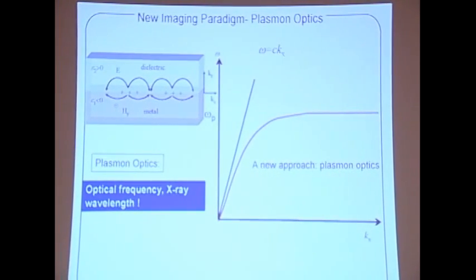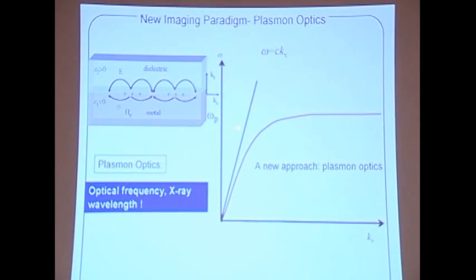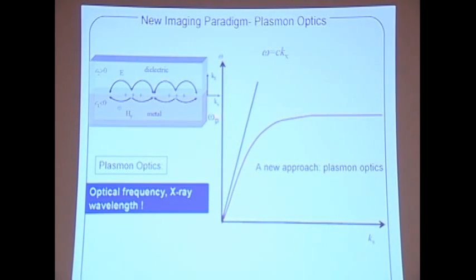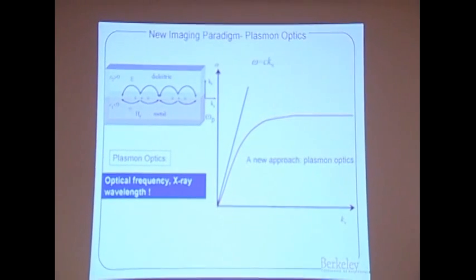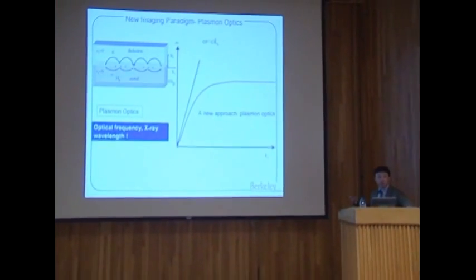Surface plasmons, as the red curve shows here, offer a different approach, where you can excite at visible frequency or a little bit of UV a very large k vector. So if you excite around here, a very large k vector surface wave can be excited. And that gives you so-called optical frequency and X-ray wavelengths. Now, X-ray wavelengths really means this large k vector and surface waves. So those are not propagating waves in free space. It's bounded at the surface. And the next question is, what are the interesting physics and engineering techniques we can use to look at this possibility for the next generation of lithography and imaging?